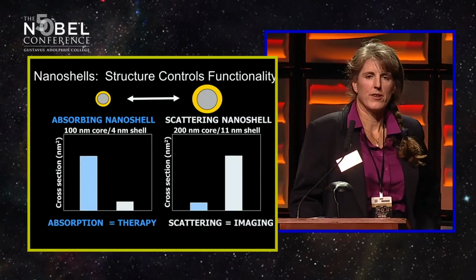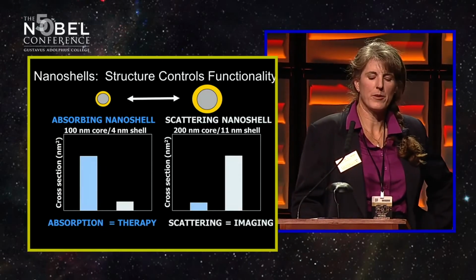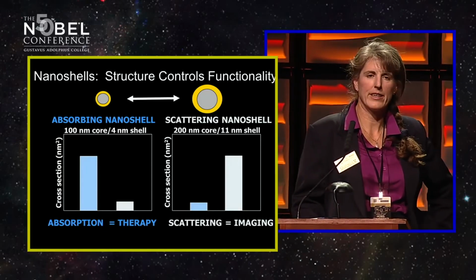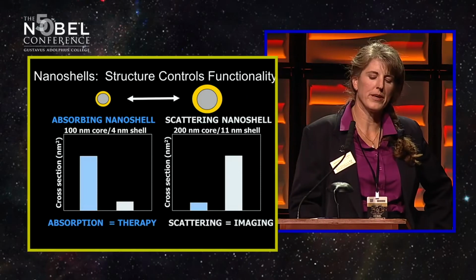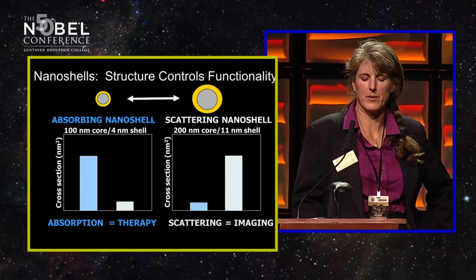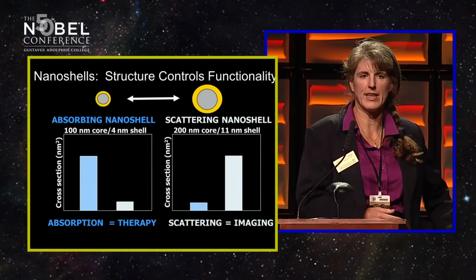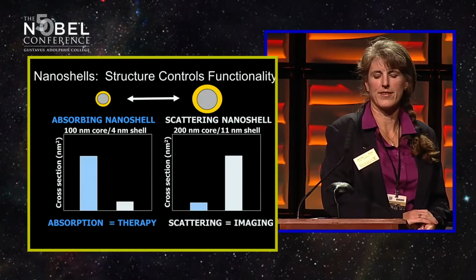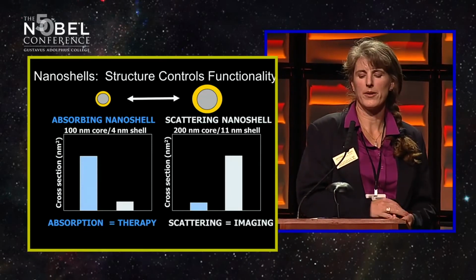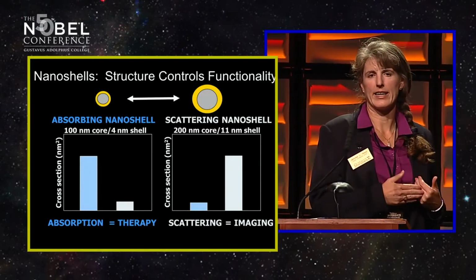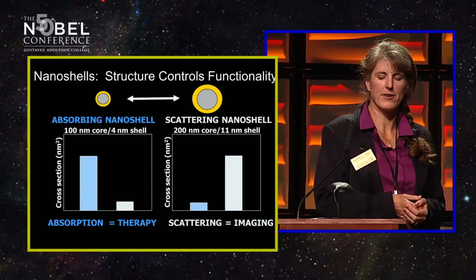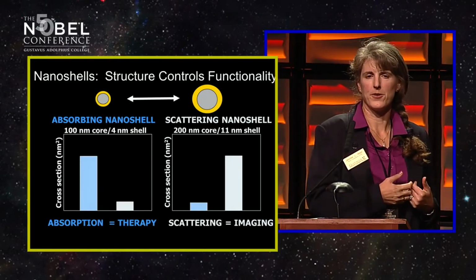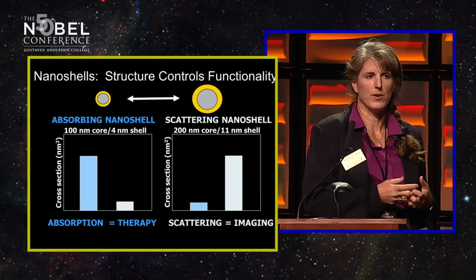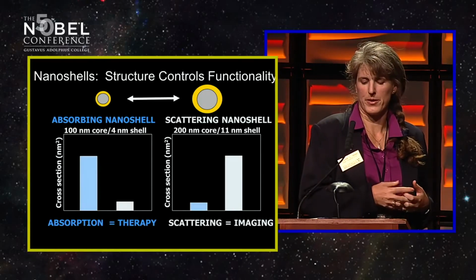I mentioned we can also control whether at that peak we mainly have absorption or scattering. For photothermal therapy, we want most of the light to be absorbed so that it's converted to heat and can damage the cells. We can also design the particles so that they'll mainly scatter light instead, and that will send light back out of your system and allow you to do things like imaging or different diagnostic tests with the particles.